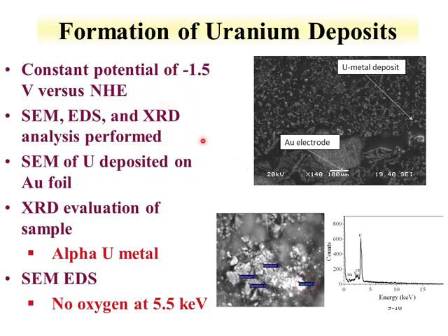The SEM definitely showed the uranium deposition on the foil, and the XRD also showed that we had alpha phase uranium. That's a relatively low temperature formation of the metal. And the EDS data shows that we did not have any oxygen formed. Now with this system, again, we use uranium-3. Doing this with uranium-6 could be a little bit more difficult because you'll have the yl oxygen present.